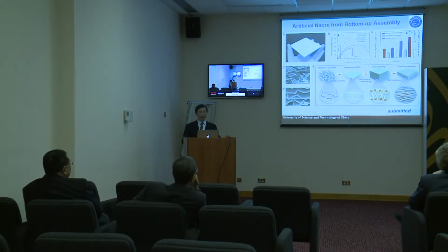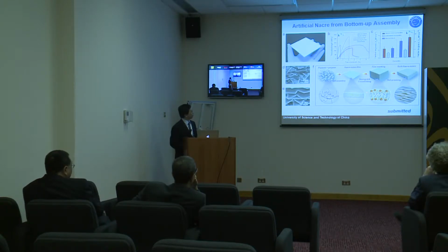And also, we apply a different strategy. We mix the nanoplates with the polymers. Then we can cast them into a nacre-mimic film. Then we introduce some polymers here. Then you can hot press them. Finally, indeed, we can get these bigger layer structures, which are quite similar to the seashell.